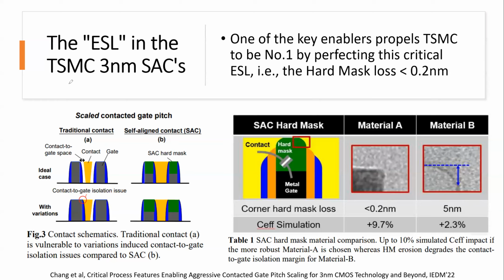And TSMC obviously just announced the success. They just celebrated the success of 3 nanometer, because the iPhone 15 Pro is using the 3 nanometer chip, and that's a big success, as you know. Then, this is the world's most famous stop layer. Currently, only TSMC can do this. Not Samsung, not Intel is able to do the self-aligned contact with such fine control. So look at these numbers, just amazing, right? You're controlling within 1 atom, and that's why TSMC is so successful these days.